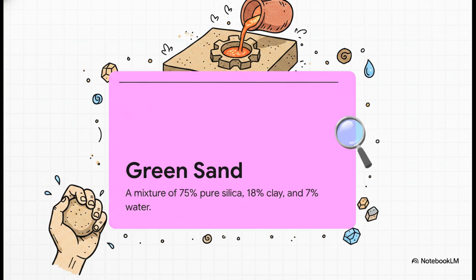Foundry casting, at its core, is just taking a molded cavity and pouring liquid metal into it. In your lab's case, that's 660 degrees Celsius molten aluminum. But the true magic of the foundry relies entirely on your medium, green sand. No, actually, scratch the image of the beach. This isn't regular sand. It's a highly specific engineered mixture of exactly 75% pure silica, 18% clay, and 7% water. This exact ratio gives it the perfect adhesive and porous properties.